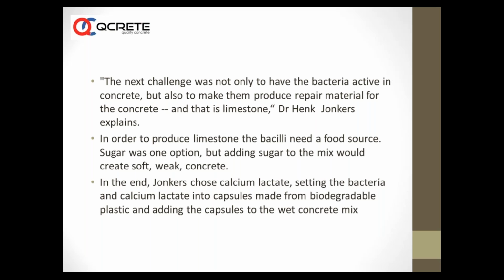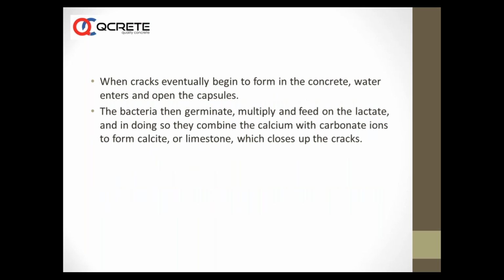In order to produce limestone, the bacilli need a food source, which is sugar, one option. If you add sugar, it is a retarder. In the end, Jonkers chose calcium lactate, setting the bacteria and calcium lactate into capsules made from biodegradable plastic and adding the capsules to wet concrete mix. When cracks eventually begin to form in the concrete, water enters and opens the capsules. The bacteria will then germinate, multiply, and feed on the lactate. And in doing so, they combine with calcium and carbonate, forming calcite or limestone, which closes up cracks. So calcite or limestone is formed and it fills up the cracks.